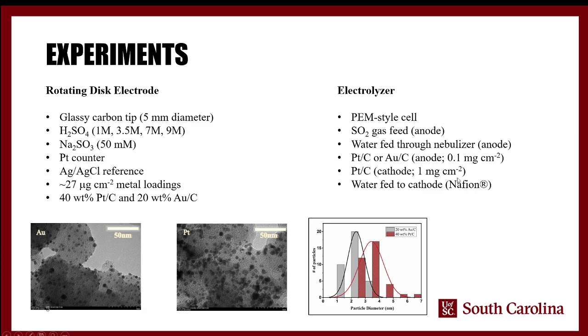And so you can see down here at the bottom pictures of the gold and platinum catalysts. Both were very small. This figure here shows the particle diameter. The gold was on average about a nanometer or so smaller than the platinum, but they were both very similar in size. And so, we made sure that we had catalysts that were reasonably close, so that size effects shouldn't be a big issue here.